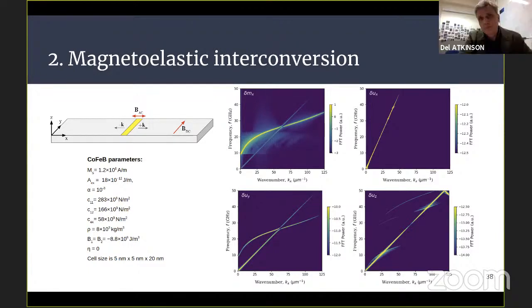Yes. These absorbing boundaries are typically used in simulations because there is no damping outside the material, so the wave is reflected in simulations. In reality, there are other damping phenomena like thermal damping, so these reflections are not realistic. If we allow these reflections to happen, you only get the normal modes of the waves. And in experiment, we have enough space for this to be damped. So these reflections at the edges are unrealistic and need to be contained in the simulation. This is very typical of simulations with waves. We need these absorbing boundaries.